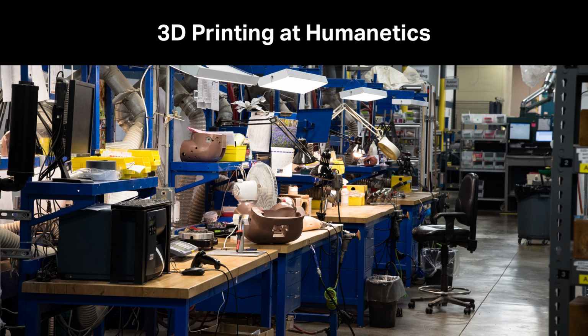So of these molds, of the ones that are appropriately sized, do you think most of them are printable with our machines? I believe the majority of what we do in-house, yes, we could make molds. A lot of our molds right now are way bigger than they need to be. Like a lot of the silicone molds, because you use the weight of the silicone to hold the 2 halves of the mold closed, since you don't really have the ability to put screws in and hold the pieces together unless you embed aluminum plates in the silicone. The problem with doing that is when you put a thermoset mold in the oven, silicone expands at a different rate than aluminum, so it doesn't like having the aluminum embedded because it expands more and pulls away from the aluminum.